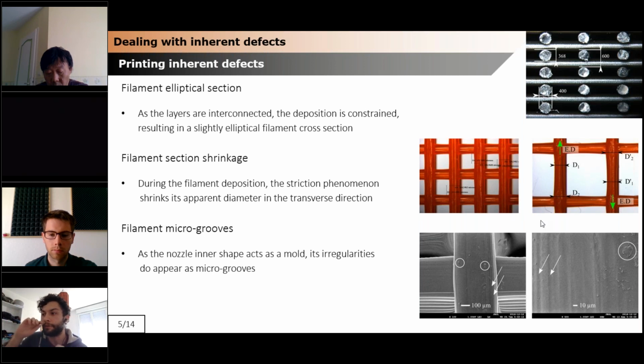Basically, the cross-section area is being reduced because of the striction phenomenon that occurs in the direction of the nozzle displacement. So this is the second type of defect that occurs. And also, since the nozzle is not a perfectly circular shape, you have those, I would say, micro corrugation and defects that are present originally on the manufacturing of the nozzle itself.